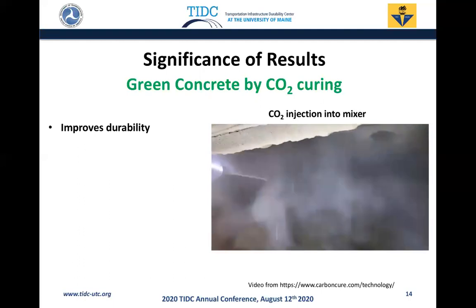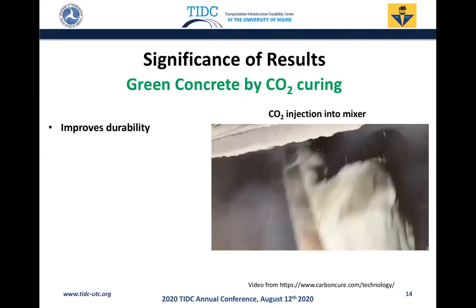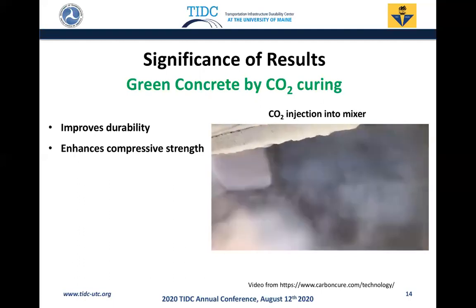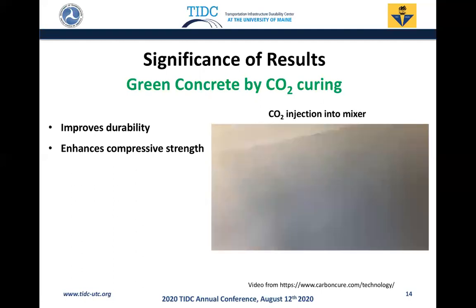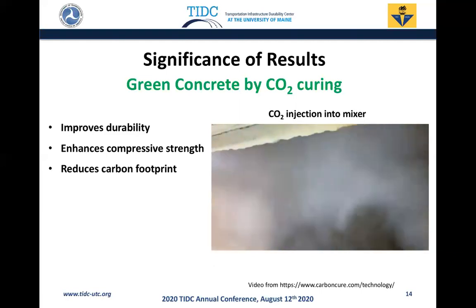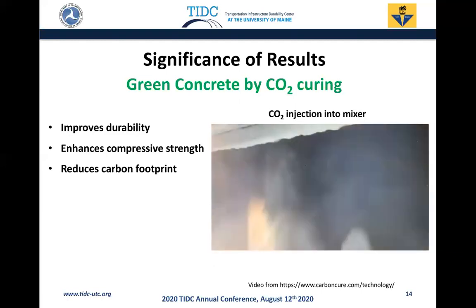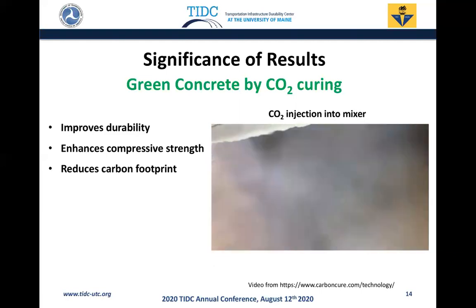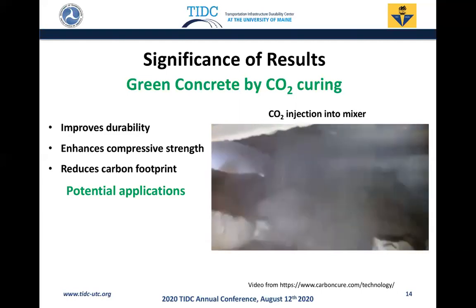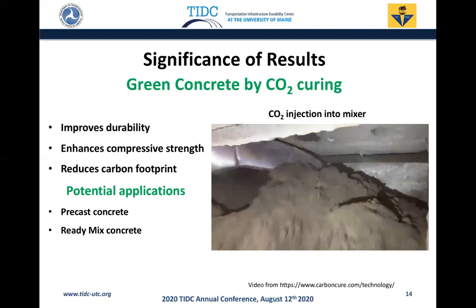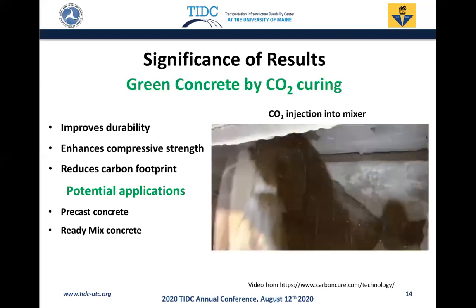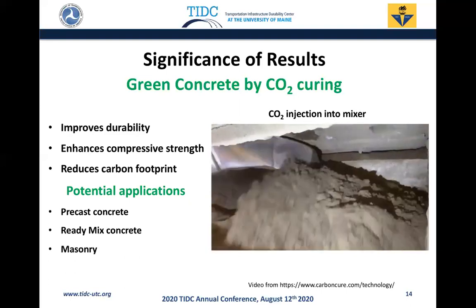Using this method, we can improve durability because we have a denser microstructure. It enhances compressive strength. It reduces carbon footprint because actually we are consuming CO2, carbon dioxide. Potential applications could be in precast concrete, in ready mixed concrete, and in masonry.